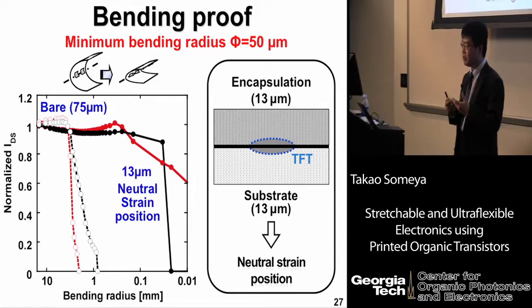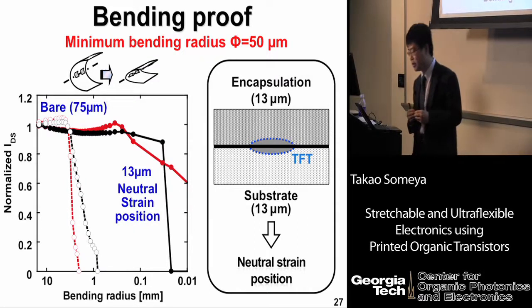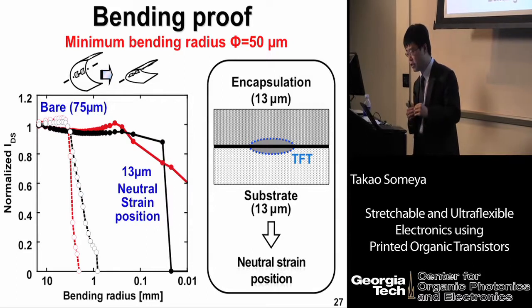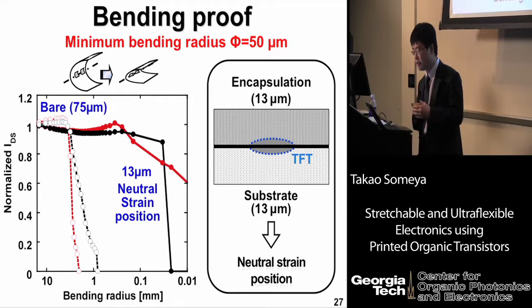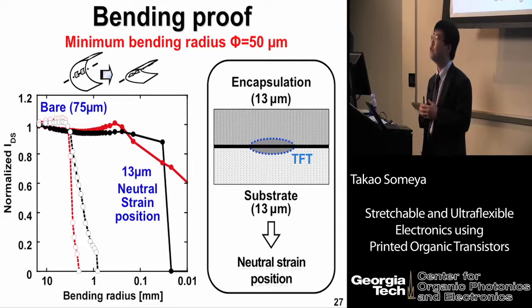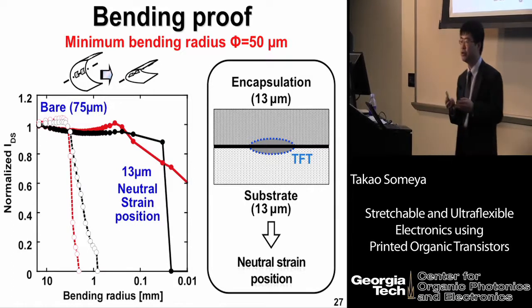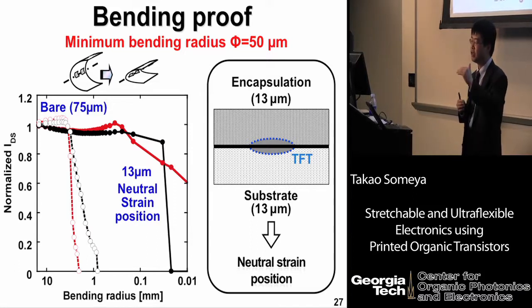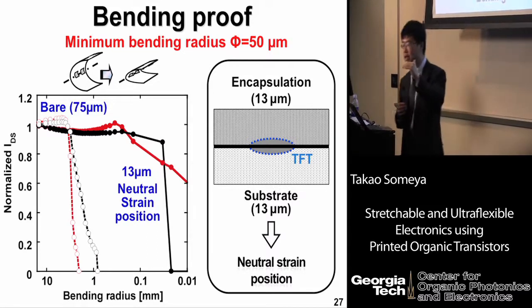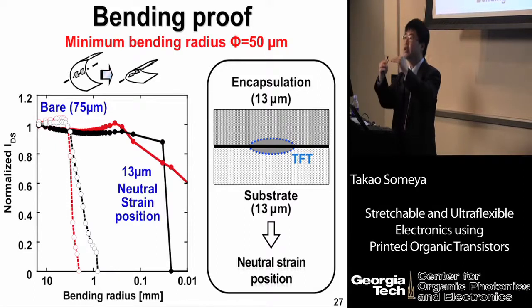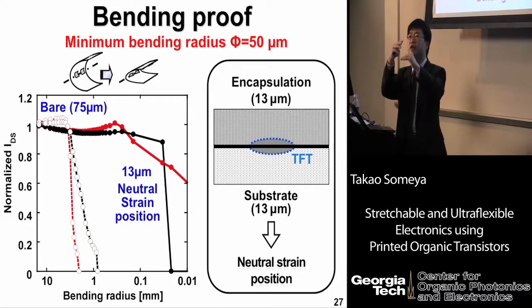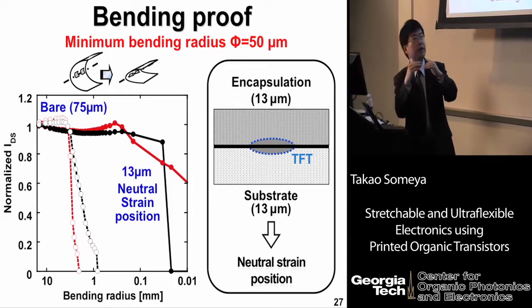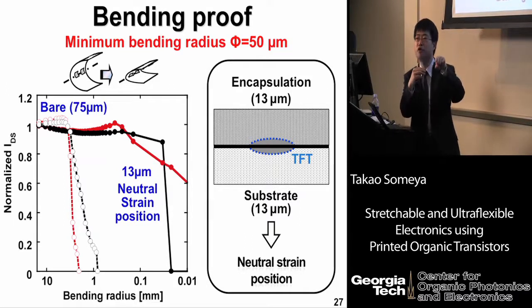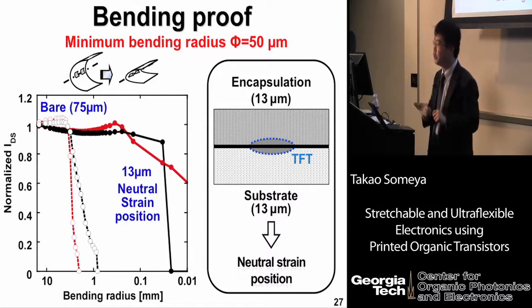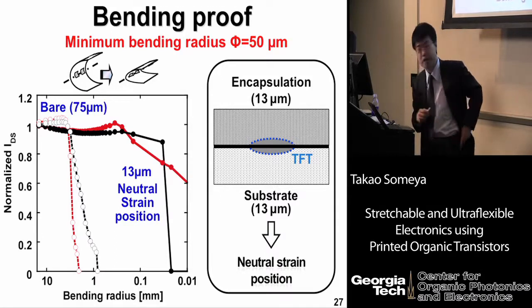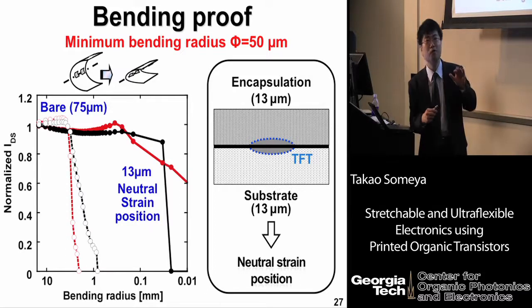So now I'd like to show you the bending experiment. If I make the organic transistors on 75 micron plastic film, the minimum bending radius was 4 millimeters. However, we can do a better job if I manufacture similar organic transistors on 13 micron plastic film that is covered by a 13 micron thick encapsulation layer. In this way, the organic transistor can be set at a neutral strain position to avoid strain-induced phenomena. So now the minimum bending radius is as small as 50 micron.